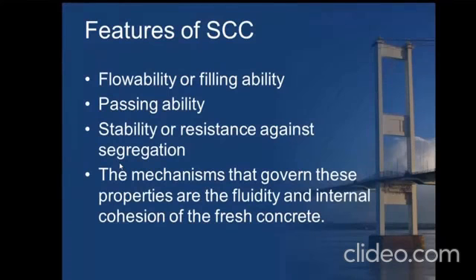The strength properties of SCC are very similar. You only need to cast a cube, a cylinder, and a prism in order to test the compressive, flexural, and split tensile strength of concrete. But in terms of workability, we have a lot of tests as per the Euro standards in order to ascertain whether it is able to pass through the reinforcement without any delay. We actually take the time that is traveled by the self-compacting concrete in passing through all these molds.